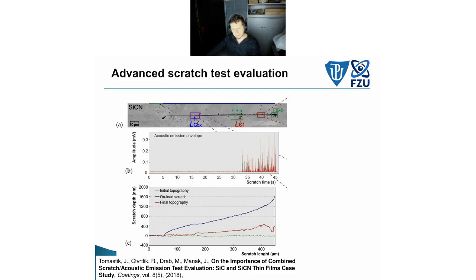Here we can see scratch tests, and from the image observation, we would see just something happening here, and nearly nothing happening here. The depth change record shows something happening here during onload. We cannot see it so much. And the final topography shows this small jump, but it is on the order of 200 nanometers, which means it's definitely not the coating. I didn't describe the thickness of the coating in general. We are talking about 2 to 3 micrometers. So this 200 nanometers is definitely not the coating itself. It's the oxidation layer, which was scratched off.